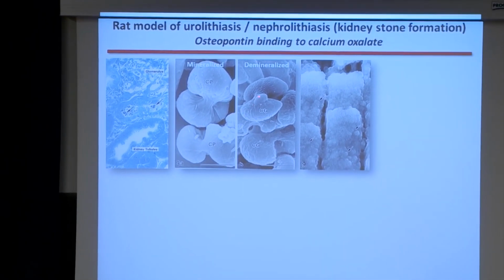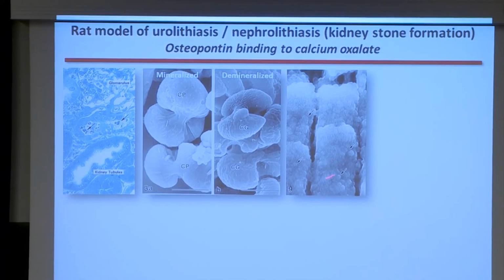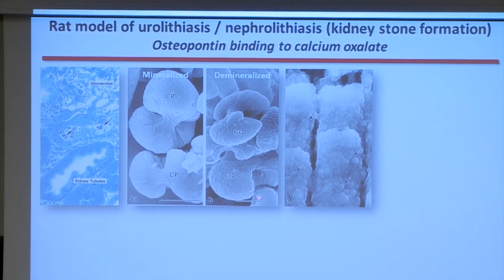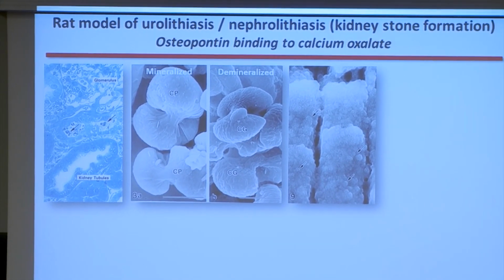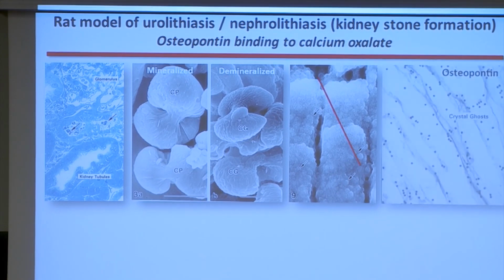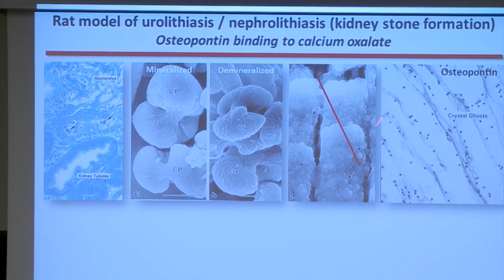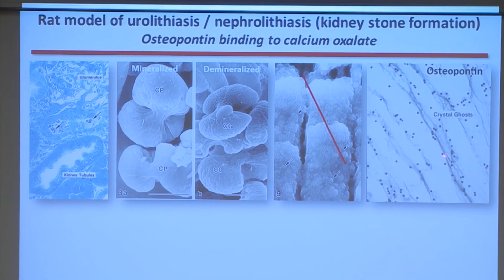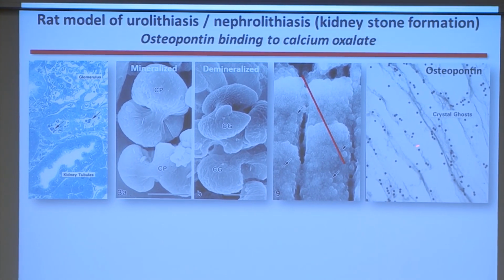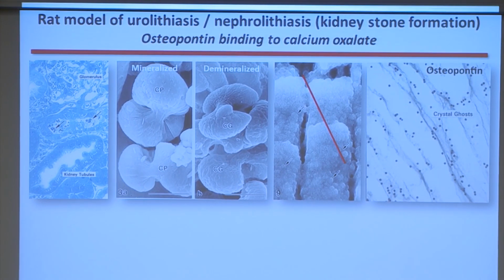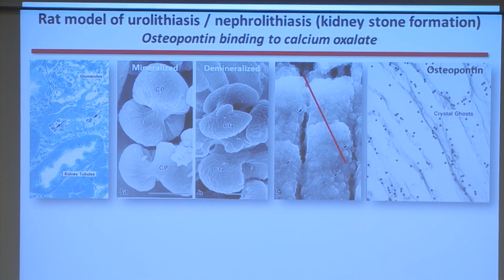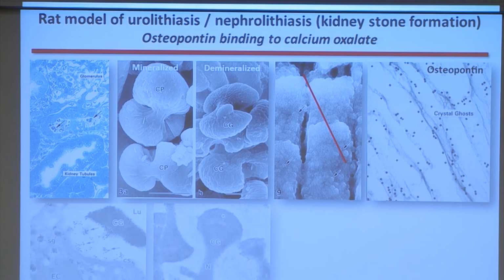And when you zoom in at the crystal surface, you see individual tablets of calcium oxalate. You see this lumpy, bumpy stuff at the surface. What is that? Well, that's a protein coating. If you cut it and section it and do some immunolabeling, in this case for osteopontin, you see that the calcium oxalate is covered by a coating of, we're guessing, inhibitory osteopontin.